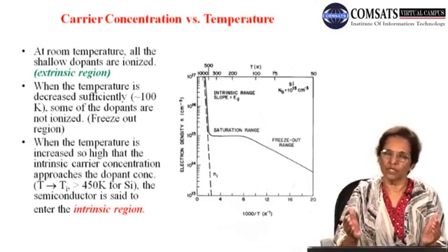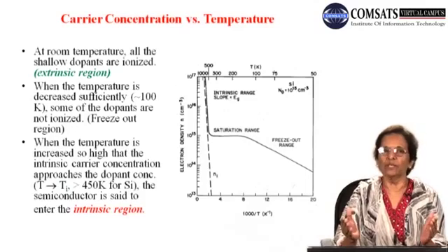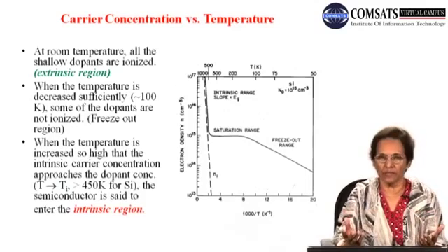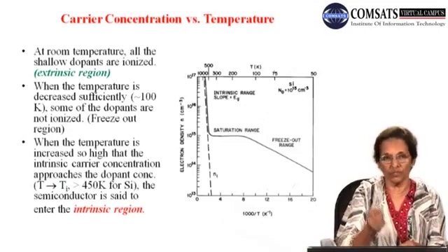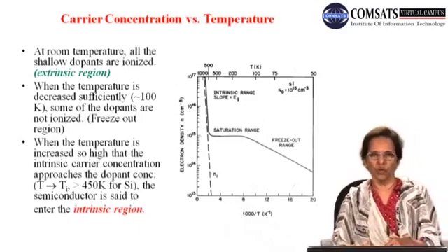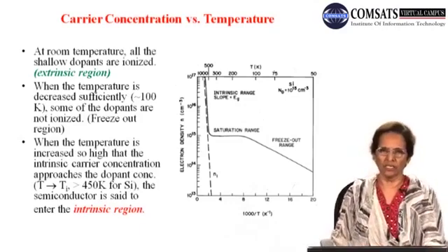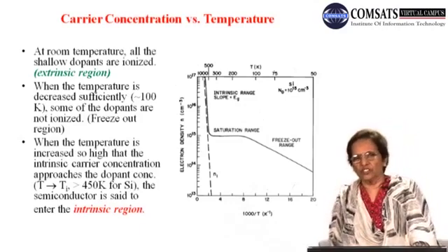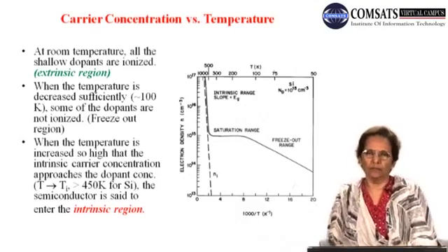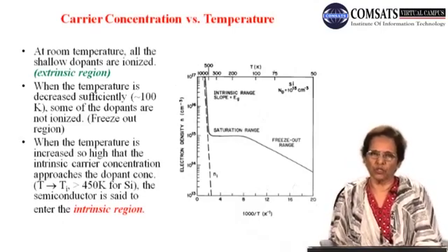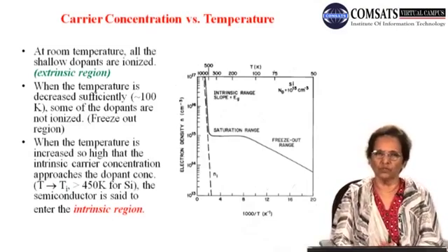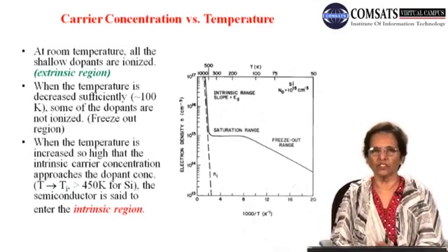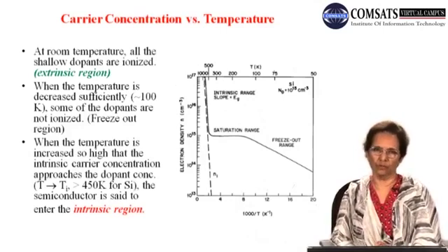all the dopant impurity will be so-called frozen, will not be ionized, because you require some minimum amount of energy. We calculated this energy before in the slide titled hydrogenic model, using the approximation of effective mass in the same equation which we use for calculating the energies of the electron in the hydrogen model.